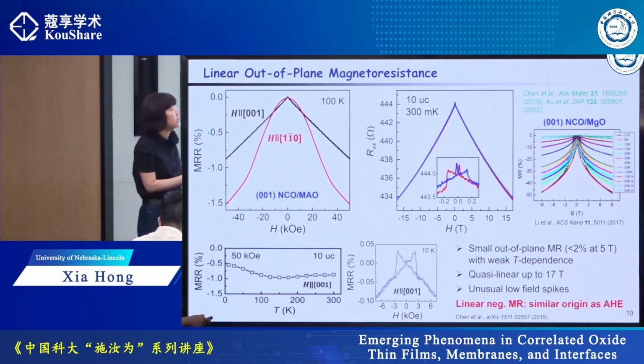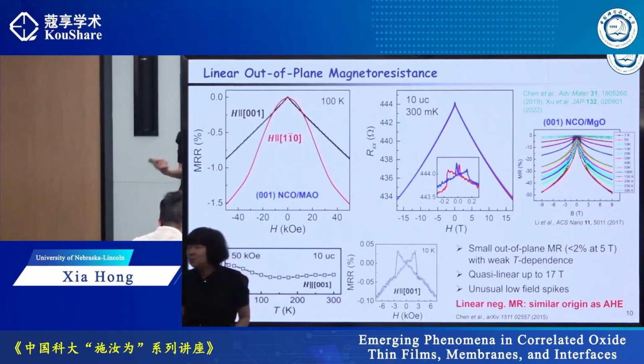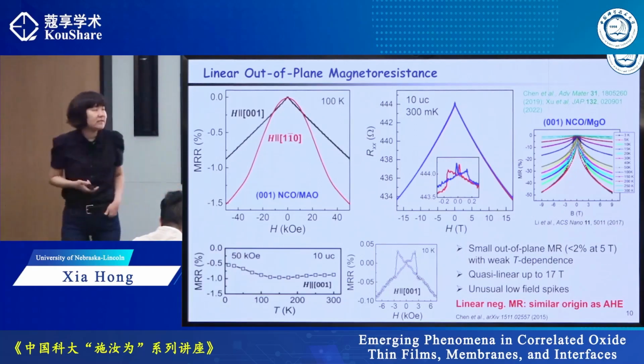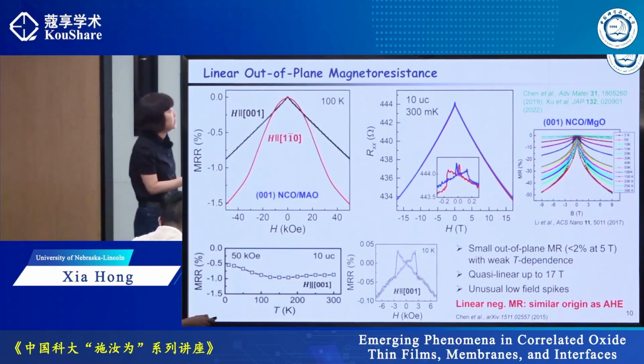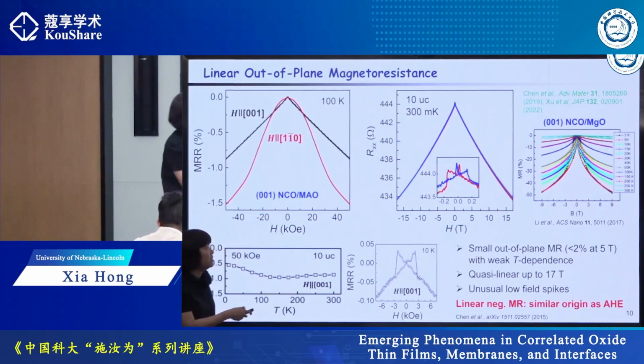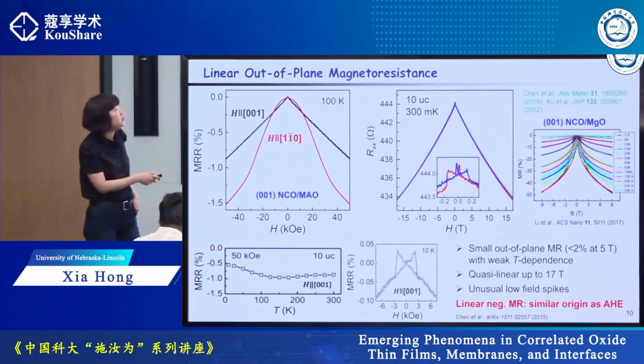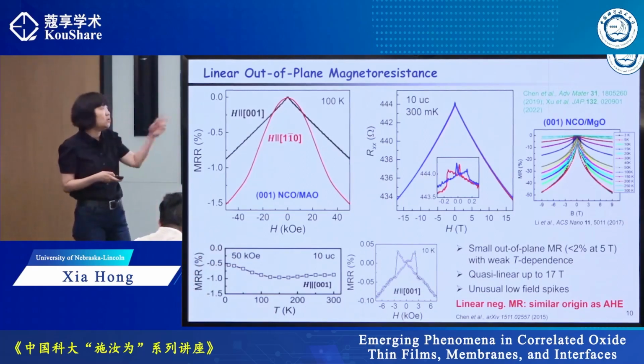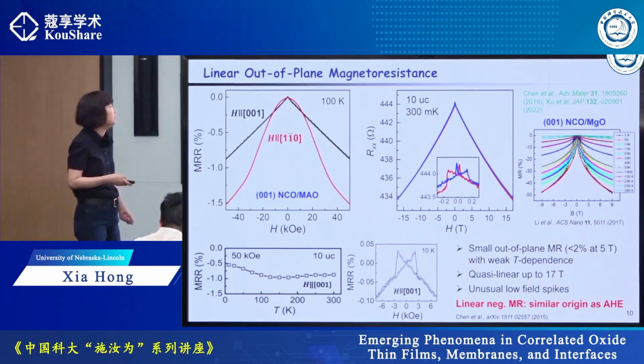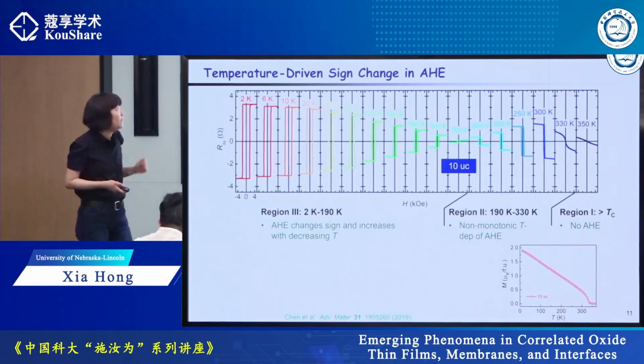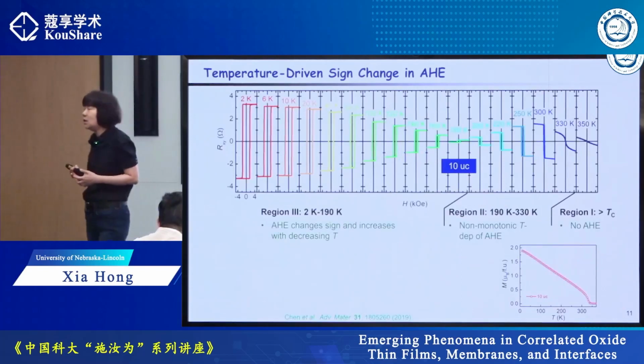And in contrast, in the older days, people grew films with more defect states. And you can see that you have much larger magnetoresistance, and it has a different shape and a high temperature dependence. So in a way, we can use magnetoresistance to gauge the quality of the sample. Then we studied the anomalous Hall effect.